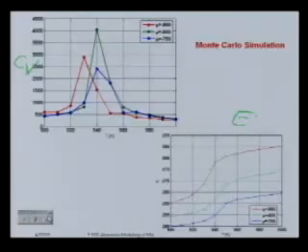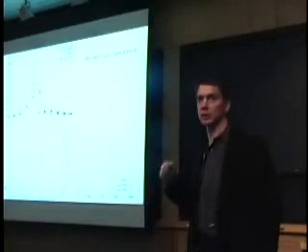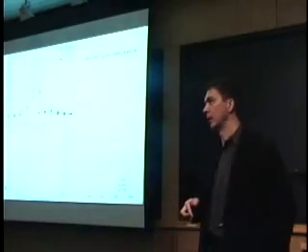And the other thing, if you really want to know that something's second order, you look at the scaling of the heat capacity with system size, and that's the really accurate way to know that something's second order. Your normalized heat capacity in a second order transition, so the heat capacity per site, scales like the square root of the number of lattice sites.